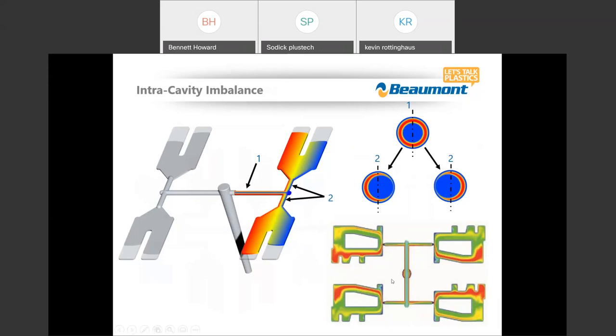And this is actually a simulation done using Moldflow. And we can actually see side to side variations within a part. So we end up with this side of the part receiving hotter, less viscous material, and this side of the part receiving slightly cooler material. So we end up with possible shrinkage variations. This cavity is going to form differently than this cavity, and thereby could possibly impact dimensions. We're shrinking different. That part is forming with completely different molecular structure within the cavity itself. So we end up sometimes with 4 cavities where we see this kitty corner effect, where these two parts will shrink or form completely different than these two cavities kitty corner to each other.